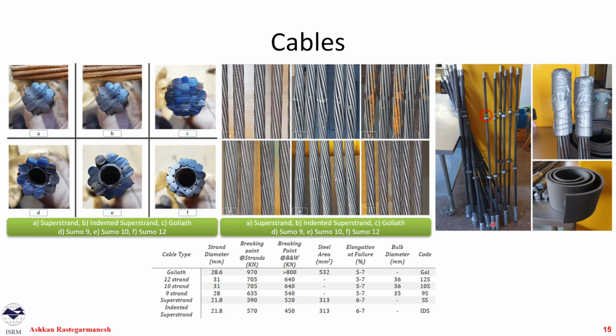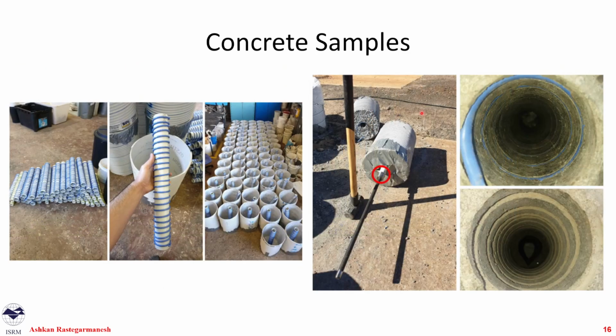So we had a foam on the bottom section of this. The reason was that we wanted to have 300 millimeter embedment throughout the test. So we added another 150 in the bottom. So when we pull out 100, 120, we still have fresh cable inside our column of the embedment. So we don't lose embedment over time as we are pulling out our cable. And some other small bits and pieces that were necessary for a test.